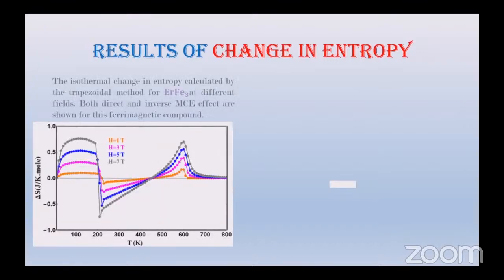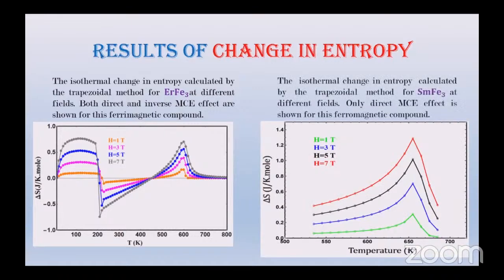Results of change in entropy. The isothermal change in entropy calculated by the trapezoidal method for erbium iron 3 at different fields, both direct and inverse magnetocaloric effect, is shown for this compound. The isothermal change in entropy calculated by the trapezoidal method for samarium iron 3 at different fields: only the direct magnetocaloric effect is shown for this ferromagnetic compound.